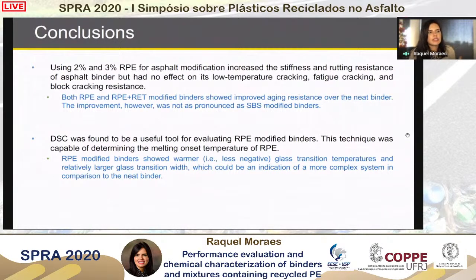And we can see that with 2 and 3% of recycled plastic, we increase the stiffness of the binder overall, therefore the overall rutting resistance of the binder, but no positive effect is being detected regarding low temperature cracking and fatigue cracking. And the DSC test was found to be a useful tool for evaluation of the recycled polymer modified binders, where we can detect melting temperature, glass transition, and the amount of crystalline fractions.